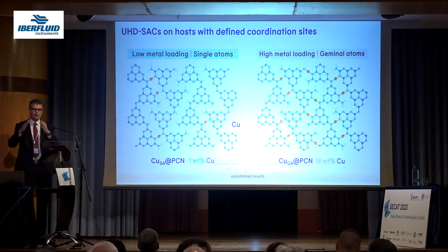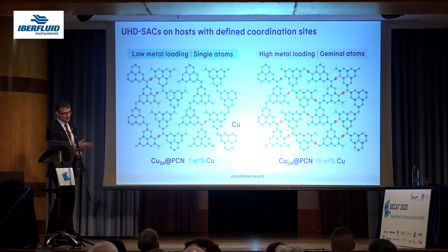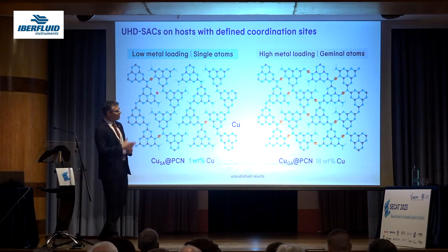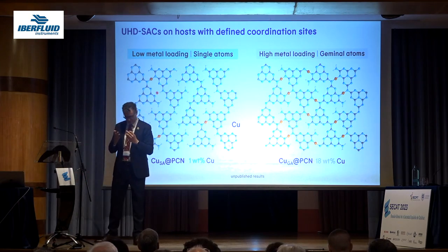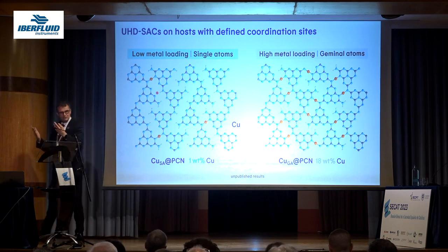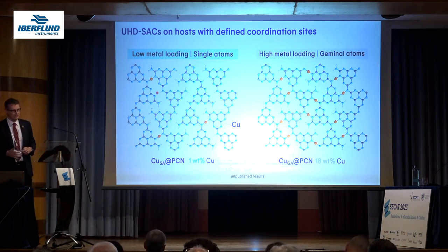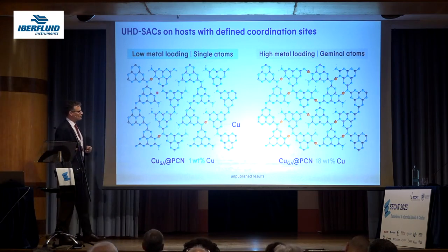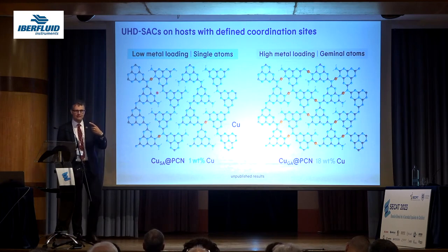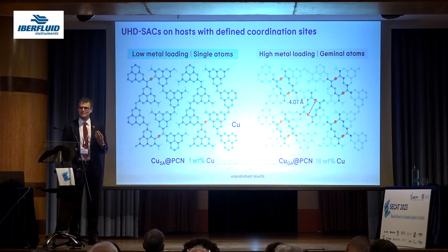So you keep populating the surface with the metal. In this case, it's copper. What happens when you increase the surface population, or the coverage of copper, is not only that you are increasing the number of active sites, but you are inducing synergies. And that is because now the copper atoms, the metal centers, are very close, four angstrom.